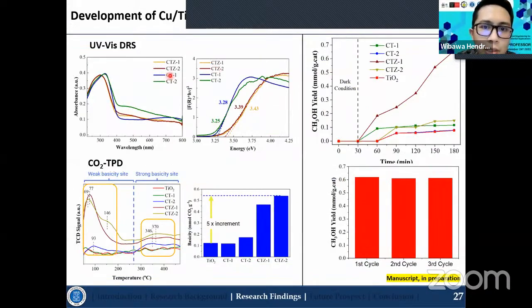And from the UV-Vis DRS, it can be seen that the band gap can be calculated, where CTZ1 and 2 are in the band gap interval from 3.3 until 3.4, because they consist of the zeolite structures, where the zeolite does not act as a semiconductor. So the band gap of the zeolite is very, very high, which can be attributed to this improvement of the band gap compared with the TiO2, where the TiO2 is around 3.25 until 3.28 electron volt. And we also did the CO2 TPD in order to find out the basicity sites of the catalyst. So it can be seen in here that there are two peaks generated.